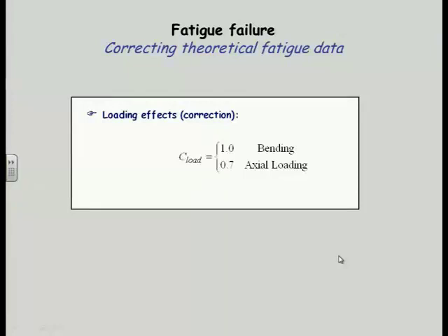So now you have lots of data out there to compare to the old rotating bending test, and it turns out that all the axial testing data is lower by about a factor of a quarter. And why? Well, the theory is, when you take a beam and rotate it in bending, you have maximum stresses at the surface and zero at the center. So the portion of the cross section that's actually highly stressed is small. When I do this back and forth, I now have F over A, the entire cross-sectional area. I have more likelihood of encountering some kind of stress riser in the whole cross section when I put it up to the same stress. That's the theory as to why we get lower numbers out of the axial test data, which are probably more accurate, by the way, than the bending.